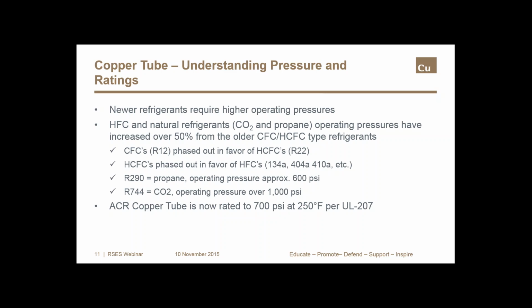Copper tubes and fittings are well suited for new refrigerants with higher operating pressures. ACR tube is rated to 700 PSI at 250 degrees Fahrenheit, and this is certified by UL 207. But manufacturers are actively promoting new products for high pressures. And we'll talk a little bit later about copper tube for extra high pressure applications.